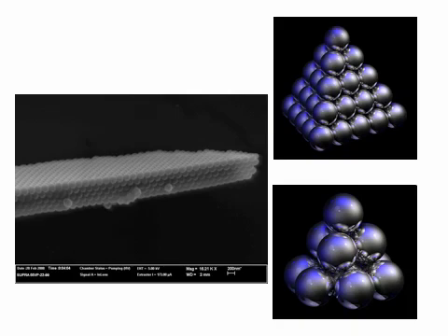There are 2 different packing arrangements for this. Which 2? Both cases have 12. Yeah, HCP, hexagonally close packed, and FCC, face-centered cubic. The top one is face-centered cubic: you have layer A, layer B offset, and layer C before you go back to layer A, so ABC, ABC. The bottom one is HCP: layer A, layer B, back to layer A. Both cases have the same coordination number and the same volumetric packing density.